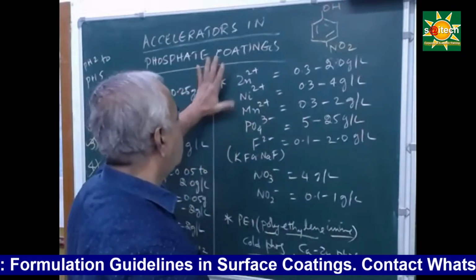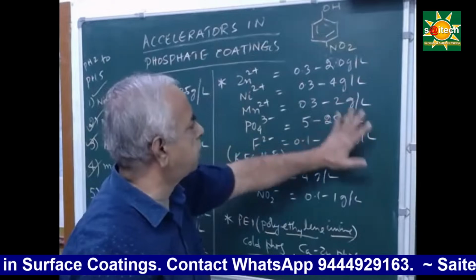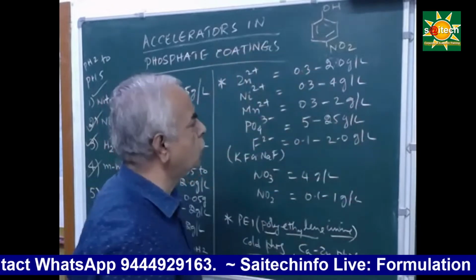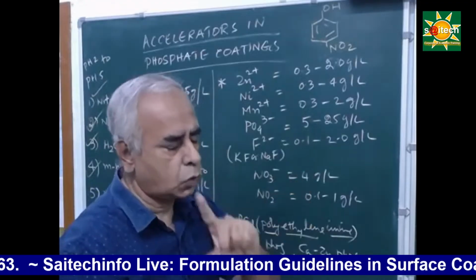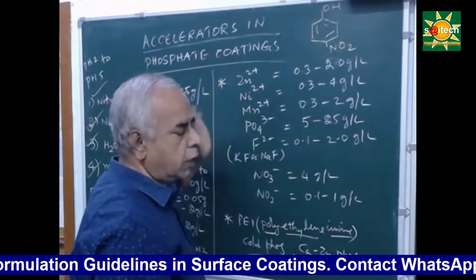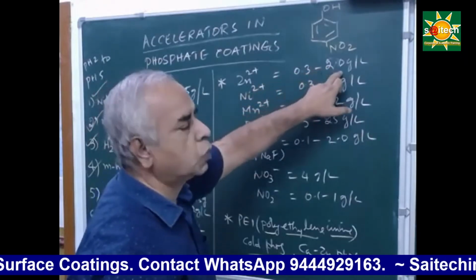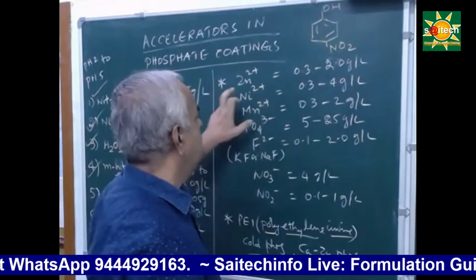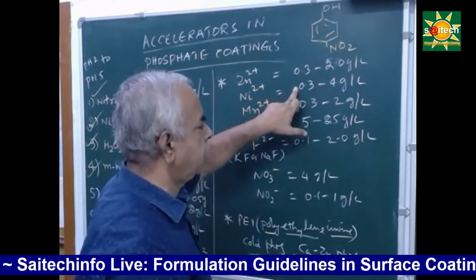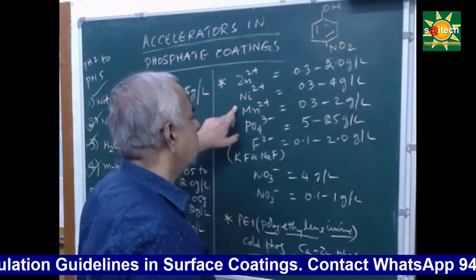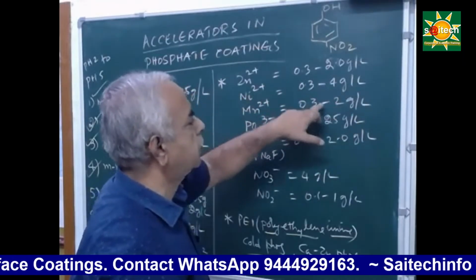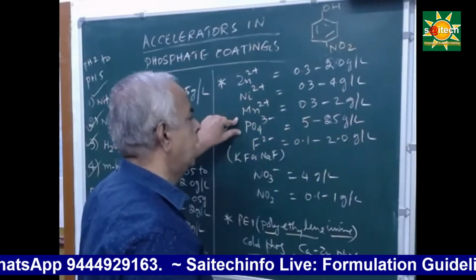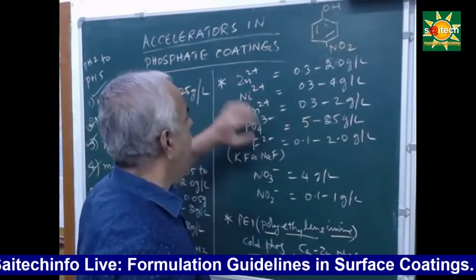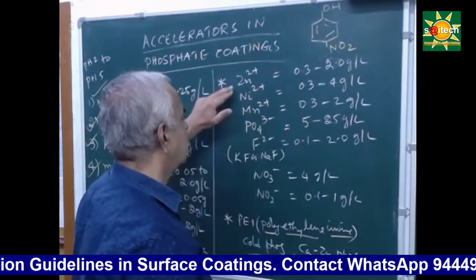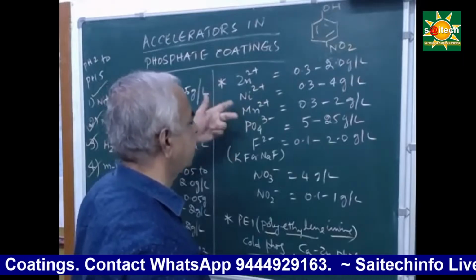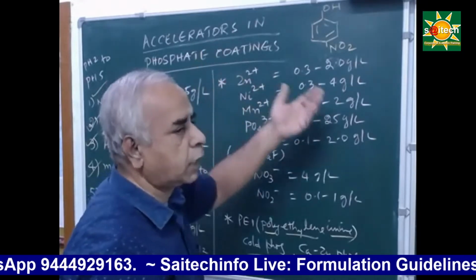Now I would like to share an important special type of trication zinc phosphate coating also. I am not giving the exact formulation; these are only guidelines. Zinc 2 plus ion may be present at around 0.3 to 2 gram per liter. Nickel 2 plus, 0.3 to 4 gram per liter. Manganese 2 plus, 0.3 to 2 gram per liter. Then the phosphate anion. Actually you are forming three types of layer: a zinc phosphate layer, a nickel phosphate layer and a manganese phosphate layer, and that is why it is called a trication phosphating system.